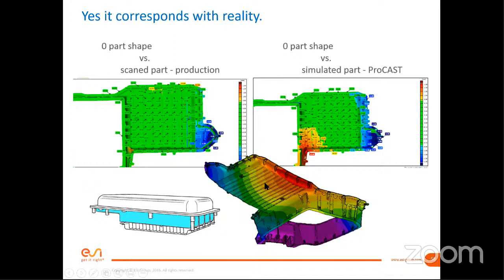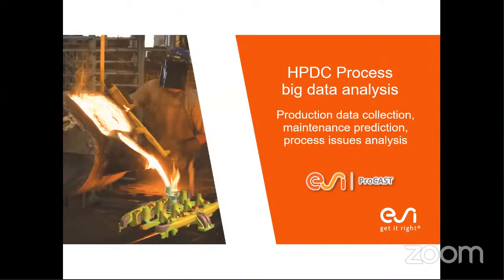And you can see during the virtual phase, without preparing any real casting, that simply you cannot achieve the goal without this supporting technological rib. And again, you can even play with the system itself. You can play with the cooling intensity for the die. You can play with many different things to prevent this bending effect. Even if you have this rib, you could see that there is some bending of the parts. This can be simply solved, or not simply, but it can be somehow solved by playing with the setup. Okay, so I will sum up.